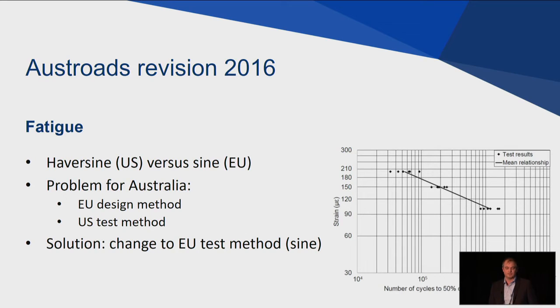The test method in Australia was based on an early version of AASHTO, used Haversine loading, and as a result, the difference in definition of strain in the test method and the design method was a factor of 2. So the solution was quite simple. We just changed to the European test method.